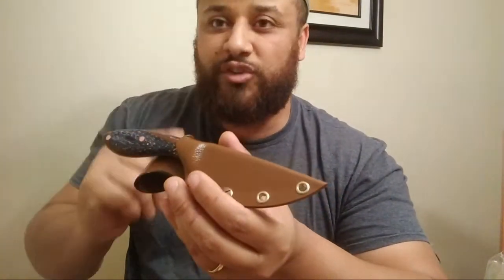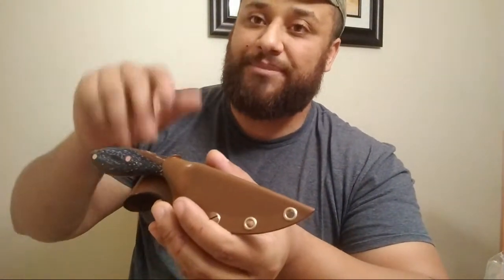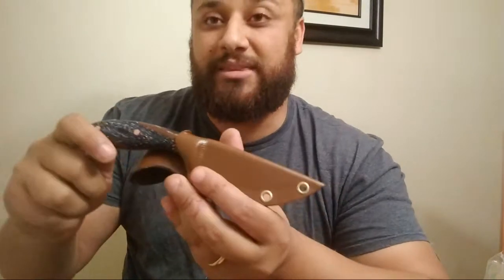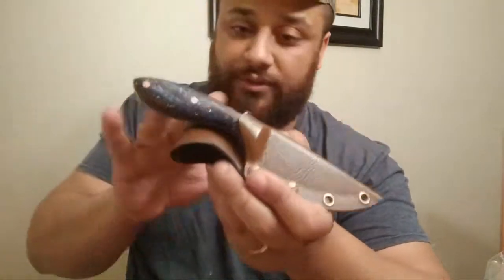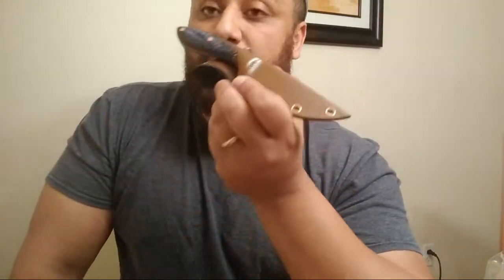We were already looking into buying Vancron 40, and Roman and I were looking into getting that. When they told us, sorry, we don't make Vancron 40, it was like, oh. But then they said they're making a new version called Vancron Super Clean. When they said they dropped the tungsten and the molybdenum, it was like they knew we wanted to make knives out of this, because we get basically 16 to 17% of almost exclusively vanadium nitrides in 1 micron to 2 micron sizes. You will never find a steel at 16 to 17% volume with this much hard vanadium hard phase particles inside it, except for this steel. Very special, very exclusive, very hard to get steel, but it's for us, by us, for knife sharpening people.